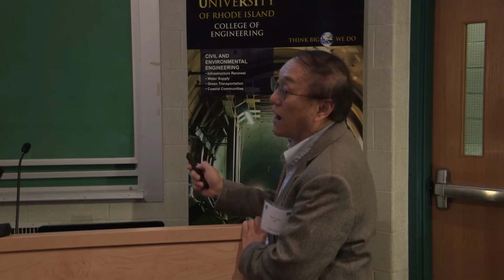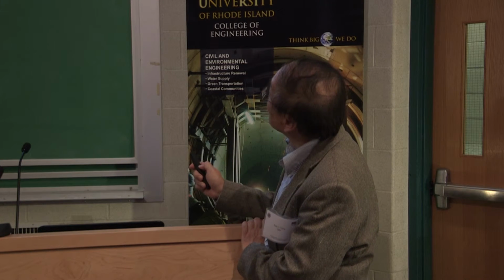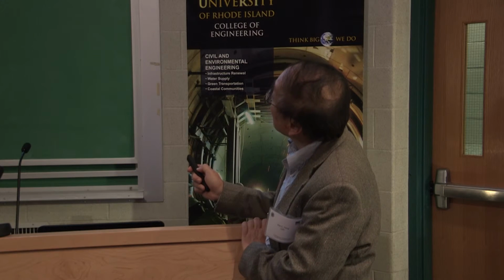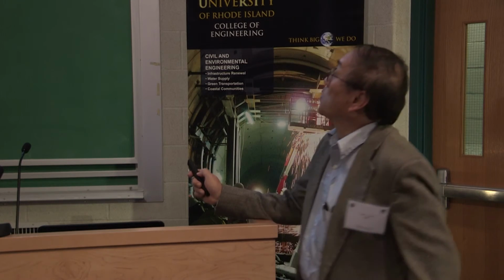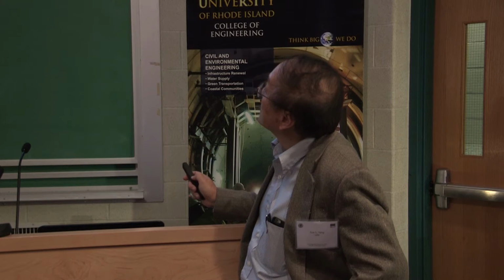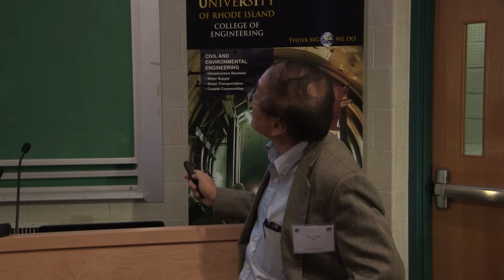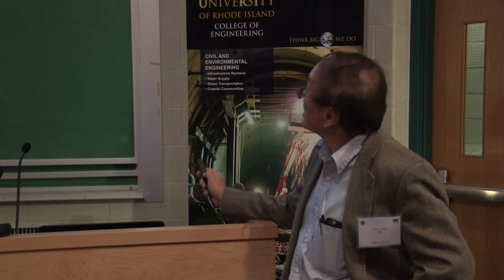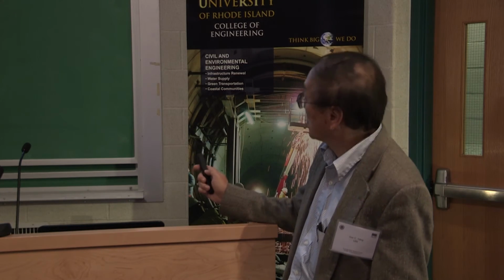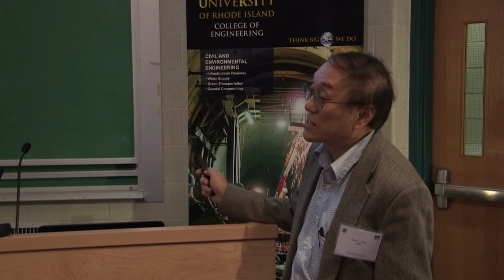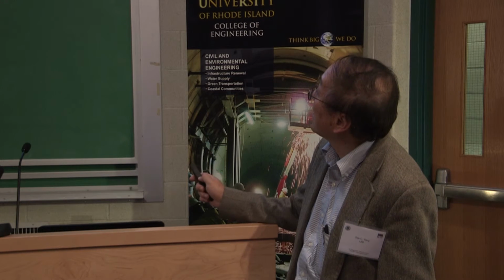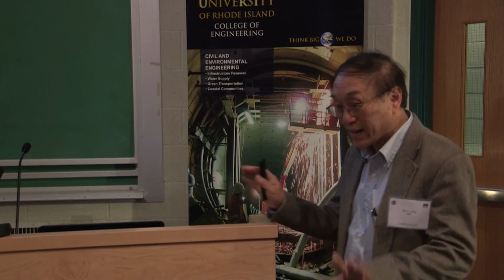Another test is that we put liquid droplets onto the roughened surface. This is initially when you put it on, and we measure the contact angle after 5 seconds when the droplet is on there. This is liquid paint which spreads. This is liquid paint that is difficult to spread, though eventually it all spreads out. But when we capture it at an earlier time, we can see this distinction. This is a high contact angle. This is a low contact angle. Eventually, they all wet the surface.